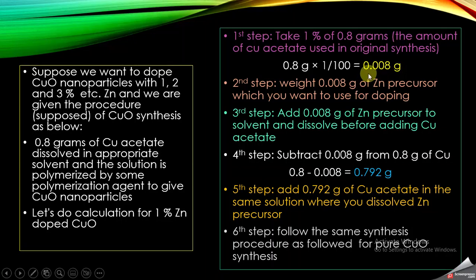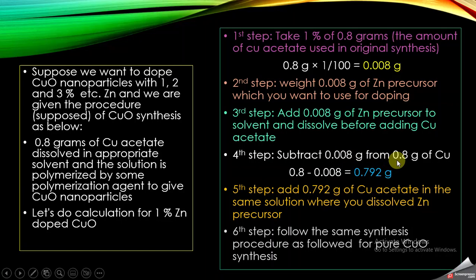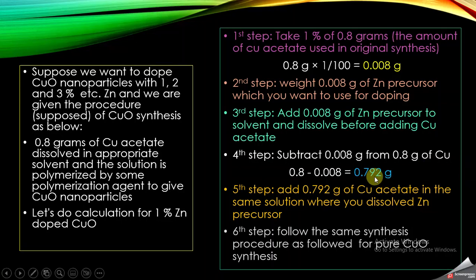The second step is that you weigh out 0.008 grams of the dopant. The third step is that you dissolve this 0.008 grams of the zinc precursor, or any other dopant, into the solvent you are using for the synthesis of copper oxide. The fourth step is that you subtract this 0.008 grams from the original 0.8 grams of copper, giving you 0.792 grams. This is the amount of copper you are now going to use in the 1% doped sample — not the original 0.8 grams, but 0.792 grams.